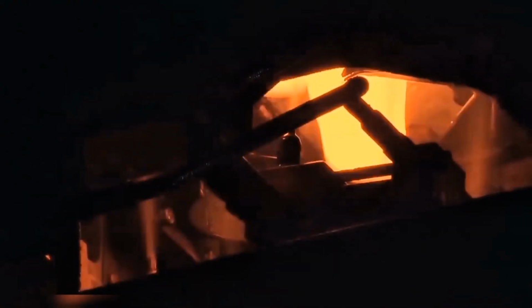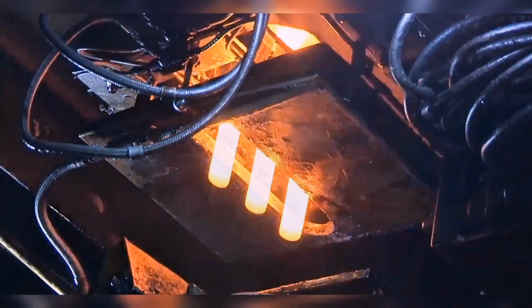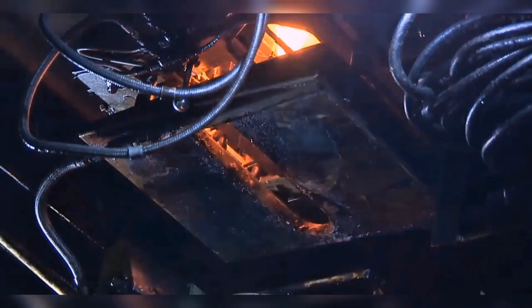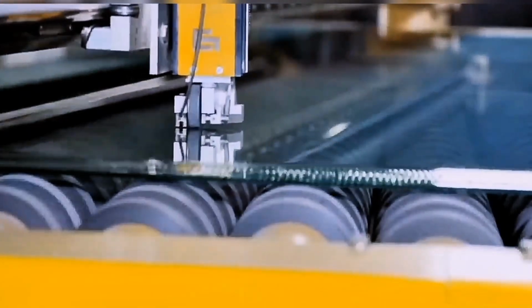Float glass forming, the tin bath, and ribbon control. Tin bath fundamentals. Molten glass is delivered from the furnace onto a bath of molten tin. Because tin is denser than glass and has suitable vapor/boiling characteristics at operating temperatures, the glass literally floats and spreads into a perfectly flat ribbon. The tin surface must be protected from oxidation by an inert positive pressure atmosphere, commonly nitrogen with a small hydrogen content. Otherwise, tin forms tin oxide that contaminates the glass surface and the tin bath.